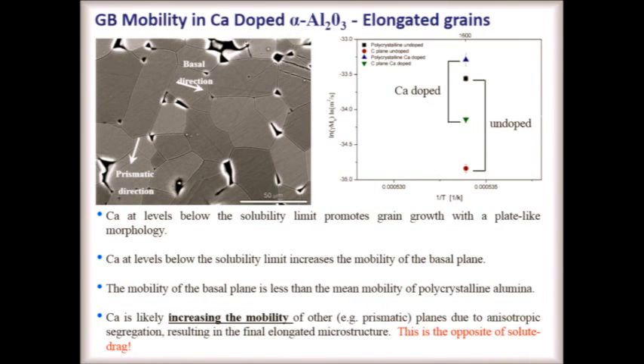So solute drag happens in alumina with magnesium, but it's not calcium. It's doing something else. It's actually doing two things. It's going there. That's the adsorption that I talked about yesterday. We're not at equilibrium here, but it's going there to reduce the energy as much as it can. In the case of magnesia, the explanation is that the grain boundaries are moving, and this cloud of solute wants to keep up, and that's slowing it down. It's probably keeping up because of energetics, but there's probably a space charge phenomenon as well at the grain boundary. Calcium has got to be doing something else.